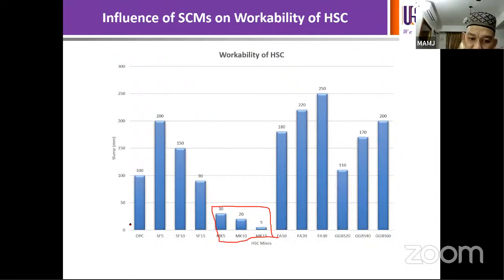All right. So in the case of other materials, for example silica fume, although it is a very fine material, since the superplasticizer is able to disperse the material effectively, and the material is having similar particle characteristic with that of fly ash, it is giving higher slump at low dosage of silica fume of 5 and 10, slight reduction at 15%. So in this particular case, greater water demand could be more dominant. And we can see that fly ash and slag both are exhibiting reduction in water demand, especially in the case of the fly ash, which we can relate to the ball bearing effect from the particle characteristic of the material having spherical shape and smooth surface, etc.